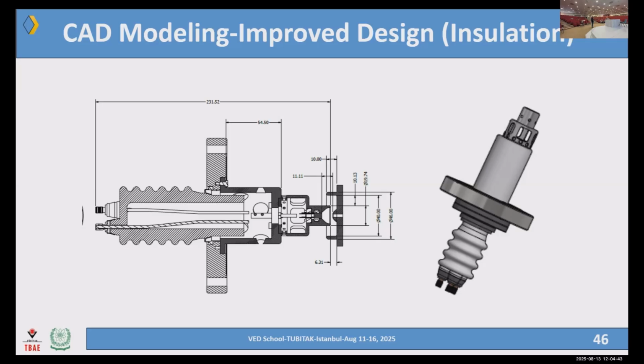And this particular gun had a jacket outside which was cooled by water, but we had to do some experiments in order to reach a stable operating point. But now we realize that there must be a complete thermal analysis of the gun. Then again, this temperature is not going to stay because the rest are cool surfaces, they are not heated. And when the temperature goes through these ceramics, they start degassing.